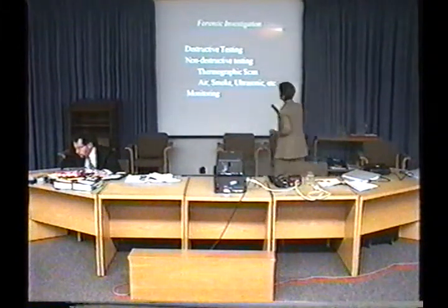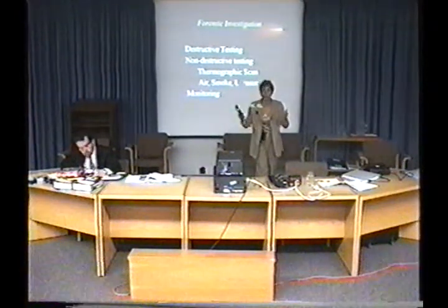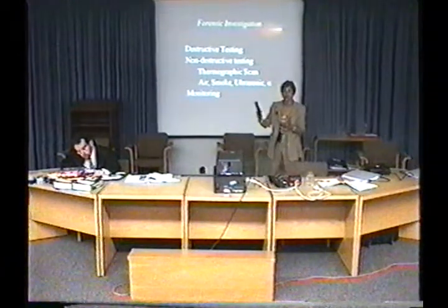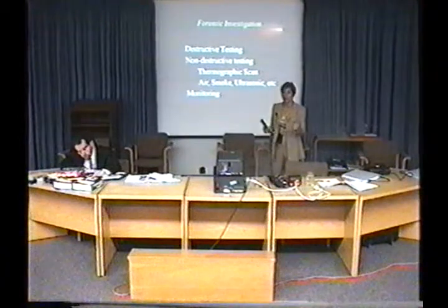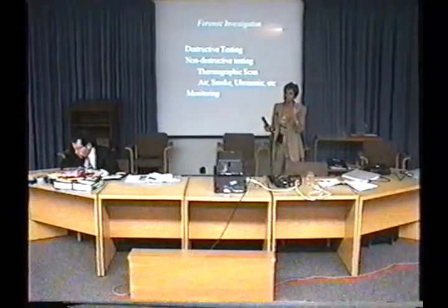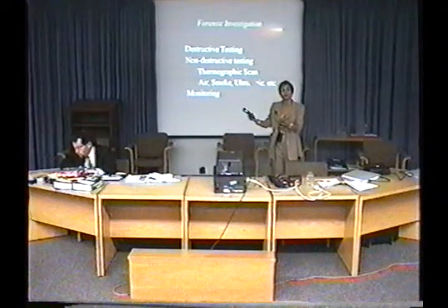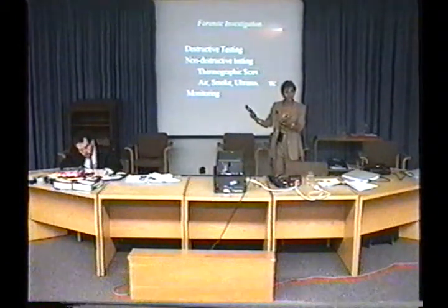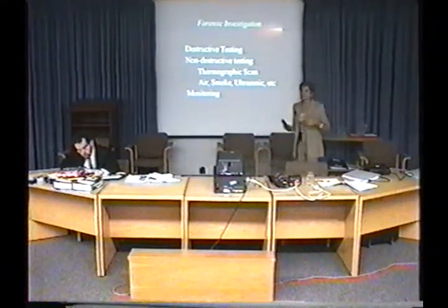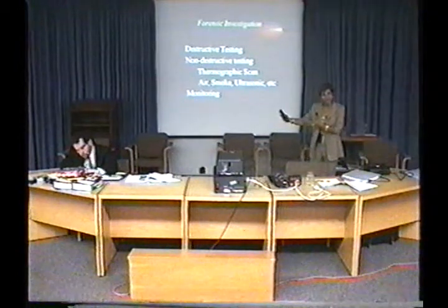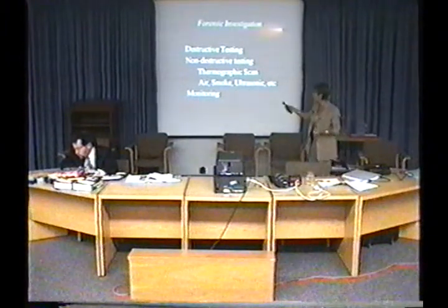The other common practice is to monitor. If you have a crack within a wall, you can monitor and establish how it is moving. And there are instruments that you can install and measures up to thousands of a millimeter movement. So you can leave it there and come back and say, yeah, in summer the crack is getting smaller, in winter it's getting wider, or vice versa. And that gives you, is it the thermal shrinkage crack? Is it a creep deflection? What type of deflection is causing those cracks?